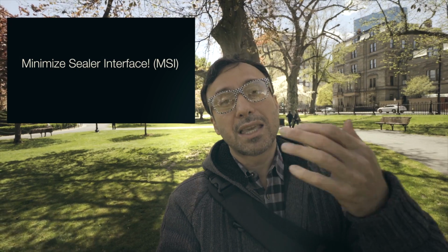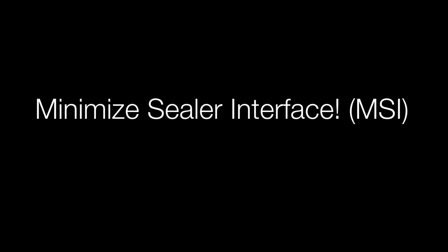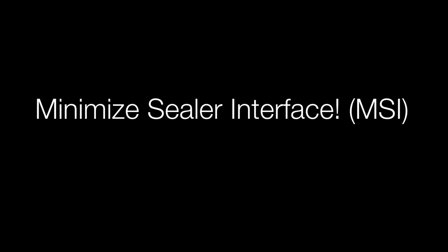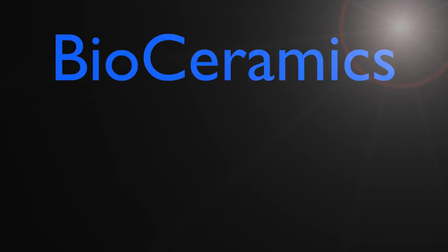So that means that the gutta percha was better than our original sealers, so we had to minimize the sealers that we had by pushing the gutta percha to replace the sealer. And that was really the beginning of our idea of obturation, and the axiom of minimizing the sealer interface has been the predominant theory that has been basically predominating the field for all of this time. So the question that comes up then is, what about bioceramics?